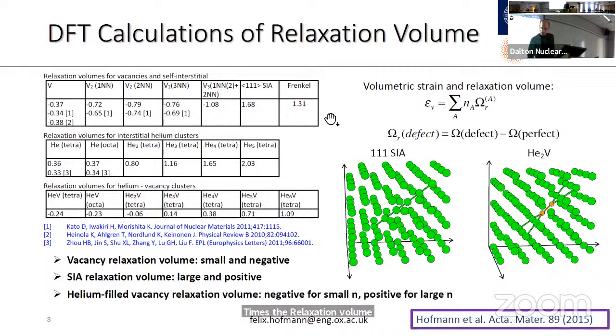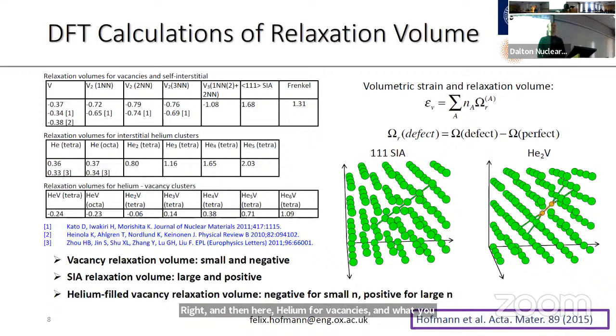So we worked out what the relaxation volumes for all of these different types of defects are. So here vacancies, here helium interstitial defects, right? And then here helium-filled vacancies. And what you find is that the relaxation volume for a vacancy is quite small and negative, so the lattice contracts a little bit if you've got a vacancy there. The relaxation volume for an interstitial is large and positive, so it's this guy here. And actually for these helium-filled vacancies, the relaxation volumes overall are fairly small.